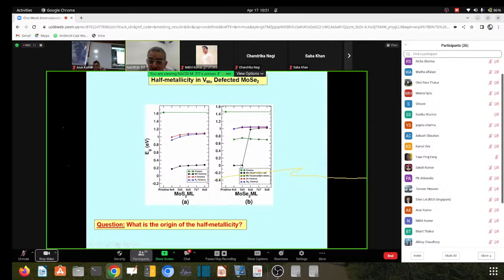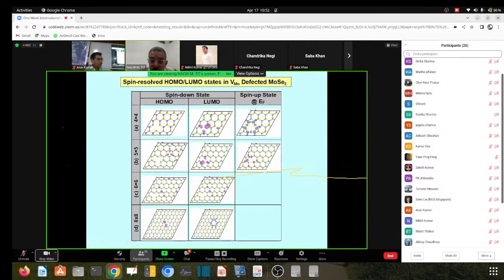In the case of 4x4, you can see here the black squares are due to the spin up, whereas the green full squares are due to spin down. Spin down is semiconducting and spin up is conducting, in the case of 4x4 and 5x5. So we investigated why there is half metallicity in this case.